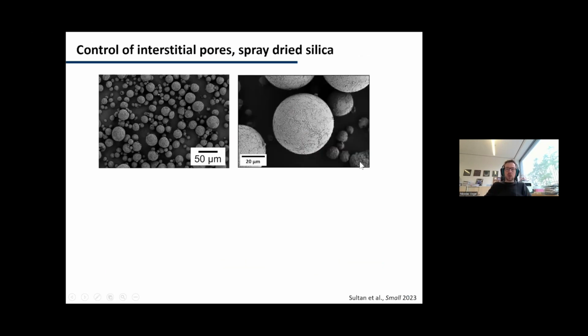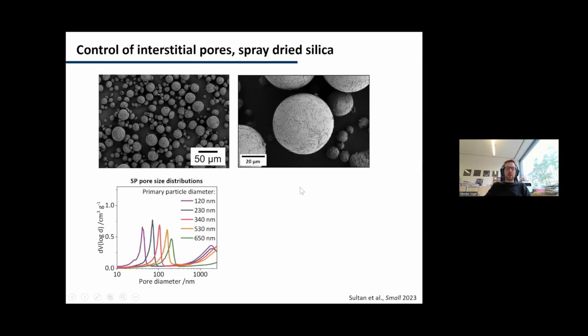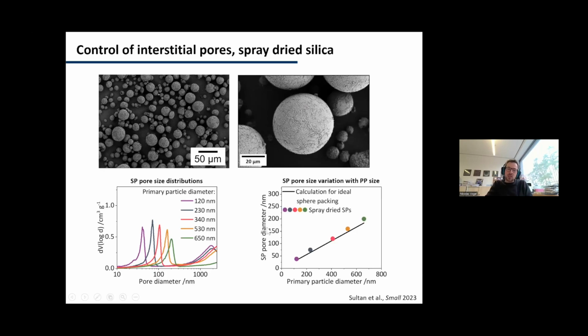Here are just some examples to show this. So here you see simple spray-dried superparticles made from fairly uniform silica primary particles. And what you can then see here, if we change the size of the primary particles, the pore diameter becomes larger. It's not very surprising, it's simply because there are bigger holes in that packing. But what is surprising to a certain extent is that even in this very fast spray drying process, the average pore size that we measure in our system is very close to what we calculate for an ideal sphere packing. And that means that even though you have a very kinetically controlled process, the ordering in our material, which you can kind of see here as well, is actually fairly good. So the pore size is reflected by what we would have for the densest packing of spheres.